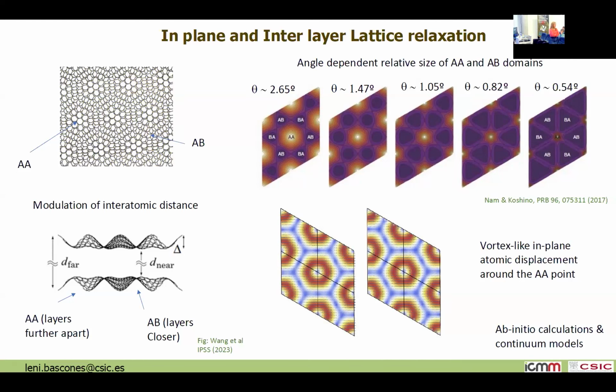Well, in twisted bilayers, so far there is disorder, which still is not completely controlled. I don't know if they have observed all this, or if they have looked at this experimentally. But at this point, the samples have domains, but not just domains of one twist angle. Normally when people do an experiment, for example with the STM, they can pick a region with some twist angle, and in some other part of the sample there is some other twist angle. Yeah, there are even domains of twist angle.